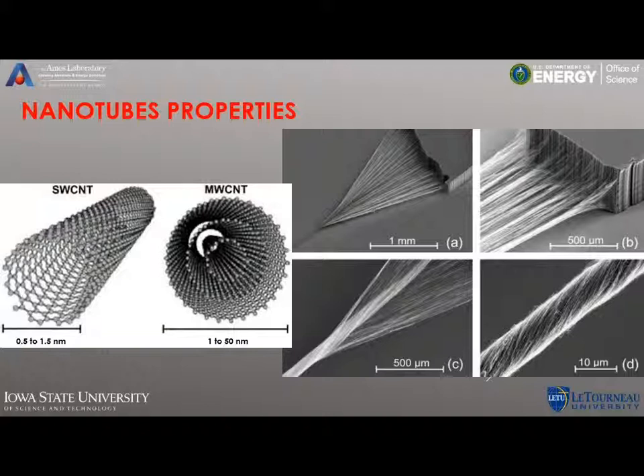The other component of these metal matrix composites were the nanotubes. You have two types principally, the single-walled carbon nanotubes and then the multi-walled. And they differ in two main characteristics. One is the diameter of the nanotubes. The single-walled are only 0.5 to 1.5 nanometers in diameter, while the multi-walled are up to 50 times that, going up to 50 nanometers in diameter. And then the other characteristic, which is pretty obvious, is that for the single-walled you've got only a single cylinder of carbon atoms, whereas for the multi-walled you have multiple layers there, which gives rise to their name.